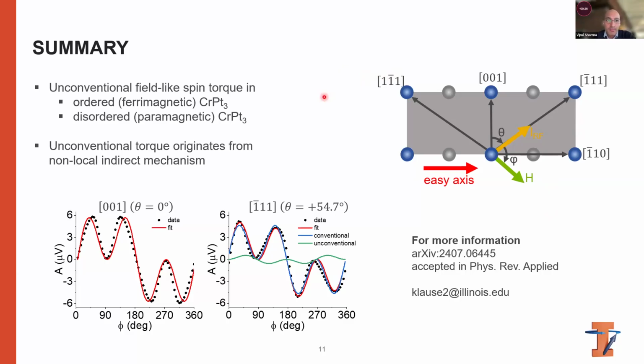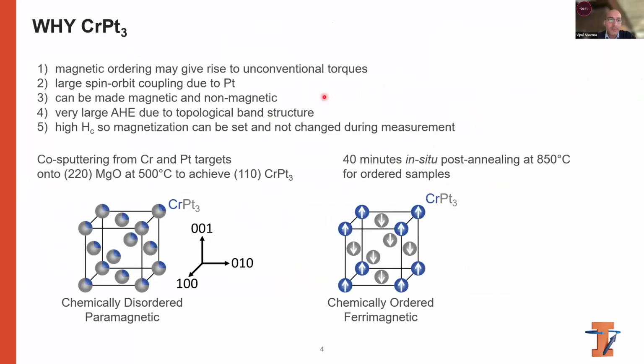Robin, I have one question. You said that you fabricate chromium platinum on MgO at 500 degrees Celsius, right? But then you need to go to very high temperature, around 800 degrees Celsius, in order to have this atomic ordering. So my question is, even 500 degrees Celsius is still very high temperature. Why aren't you getting the desired ordering, although it's crystalline but not properly ordered? At such high temperature, 850 degrees Celsius, is generally considered not very good for metals, because metals generally have some stress or other surface-related effects at such high temperature. So what do you think about it? Why does it require so much high temperature to have this ordering?